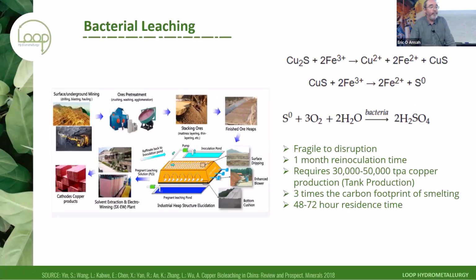Bacterial oxidation is you then start moving up to residence times of 48 to 72 hours, 2 to 3 days. So you're talking significantly larger capital costs for the size of the leach train. And I know I'm biased here, I know I'm an inorganic chemist, but my fundamental criticism of bacterial oxidation is bugs die. You get an interruption to your process, you lose power to your process, your bugs die off, and you're going to spend a month re-inoculating and getting back into operation. You know, in our system, we lose power, we turn the power back on, and 6 hours later you're back up and going. So it's just a lot more robust.